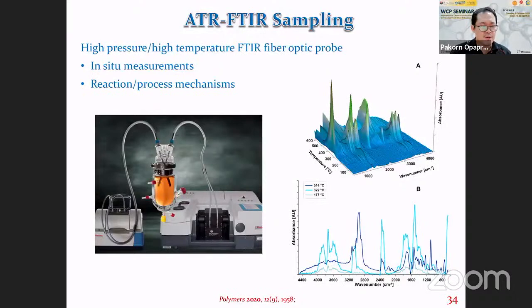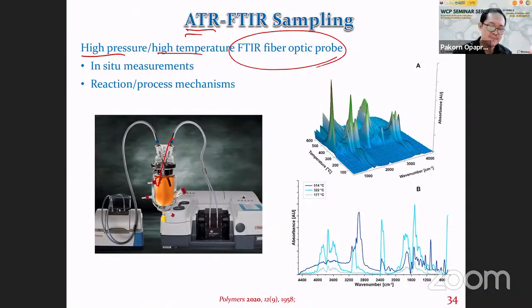And with more advanced techniques now, we can make the ATR crystal into the form of a fiber optic probe that can be used at high pressure and high temperature. As a result, we can stick the probe into our chemical reaction. For example, if you do a chemical reaction at very high temperature and very high pressure, you just put the probe in here, and you can measure the spectrum of the solution or your reaction in real time, as a function of time. When you have the result, you have many opportunities to play with it and get important information.